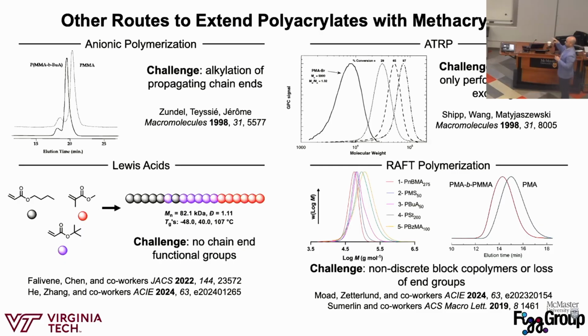The challenge with this though is that as soon as you open your flask, you're going to lose your chain end. So if I ask my students to make a library of 50 polymers where you're just changing the second block, they would have to make all 50 of those block copolymers individually, and then you're going to have some dispersity in your first block because they're not all made from the same starting polymer. So it just creates some issues if you're trying to diversify your library. So that's great, but my students wouldn't be very happy. Ideally, you start with one parent polymer and then you can derivatize that parent polymer to see the effects of the second block.